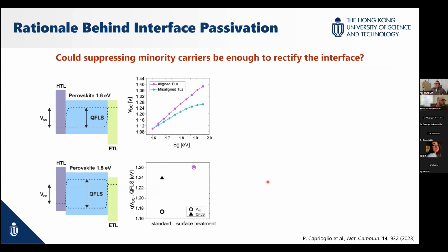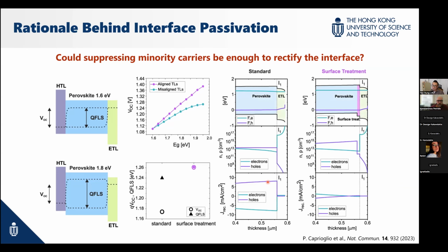We touched on this a little when we talked about the additive being pushed to the boundary. From the optoelectronic characterization, from our analysis, the charge carriers of opposite polarity have different concentrations. So one important thing is to remedy the interface and see if we are able to reduce the amount of minority carriers at the interface. For example, if we want to extract electrons, the important thing is to reduce the minority carrier, which is the hole. Otherwise, the recombination will be severe. So this is most of the passivation functionality.